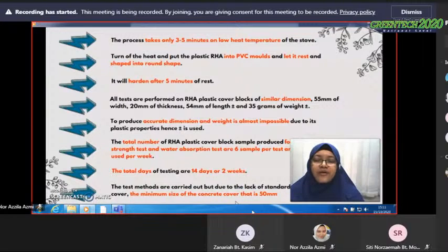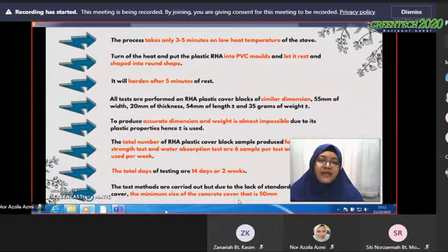All tests are performed on RHA plastic cover blocks of similar dimension. To produce accurate dimension and weight is almost impossible due to its plastic properties, hence ± is used. The total number of RHA plastic cover block samples produced for compressive strength tests and water absorption tests is 6 samples per test, and 3 samples are used per week. The total days of testing are 14 days, or 2 weeks. The test methods are carried out, but due to the lack of a standard for the concrete cover, the minimum size of the concrete cover is 50 mm.